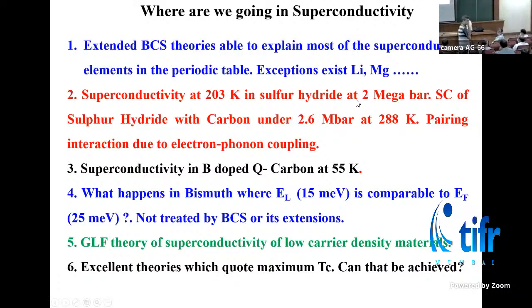Is it not possible that the high pressure is not really impacting the electron-phonon coupling, but is just making a completely new material? Say sulfur hydride reacts with the carbon and makes a new material. Yeah, it's possible. Because nobody knows what the electron-phonon coupling constant is in this. They gave a ballpark figure of 2 or something like that, but we don't know. As you said, it could be a new structure giving rise to this. But they have seen both the Meissner effect and the resistivity, so the data is reliable.